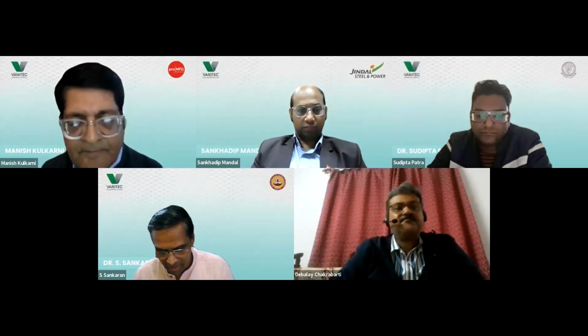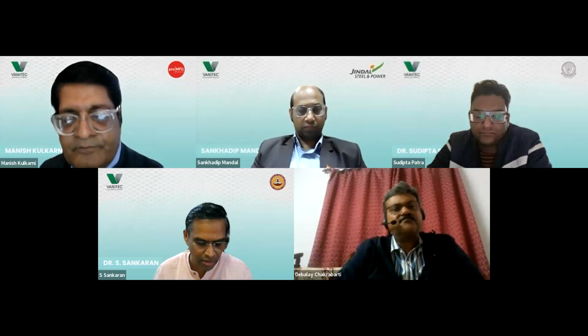Yes, thank you, Manish. The one point I want to add is that these microalloy steels, like vanadium or niobium, are amenable to forming various types of microstructures. Like Jabal has said, their response to the cooling rate is quite amazing. You can produce lath type ferrite, acicular ferrite, polygonal ferrite, or a combination or bimodal distribution and so on. These are the areas we have tested, and we have also patented some of these ideas to manipulate this and exploit interphase precipitation and controlled cooling. These are great engineering advantages one should look at to derive the desired properties.